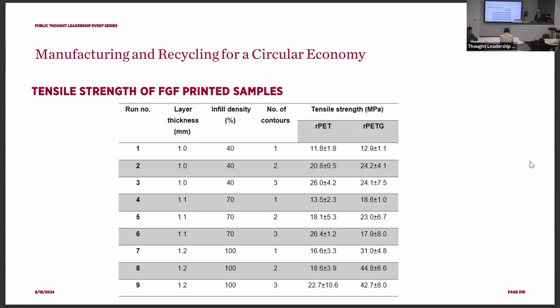And so that's what we compared. Also, you can see the contour actually influenced the tensile strength significantly for the RPET. But for RPETG, it's not that big when we increase the number of contours. But from one to two, they significantly change the values. So that means the skin thickness, or the number of contours, is really important.